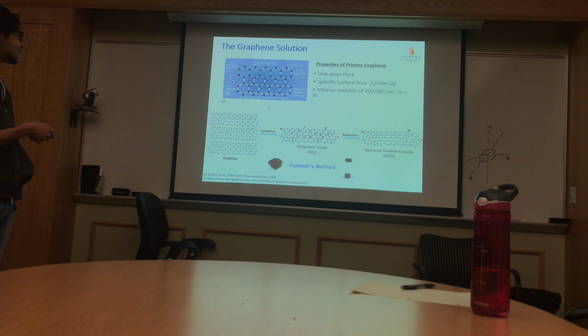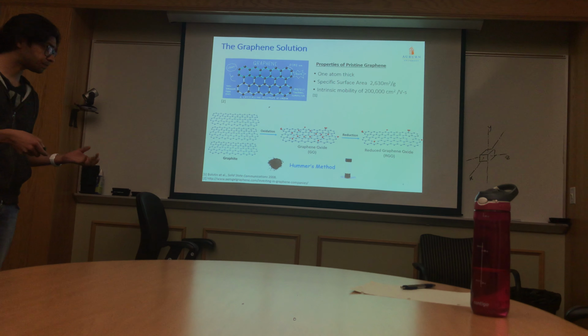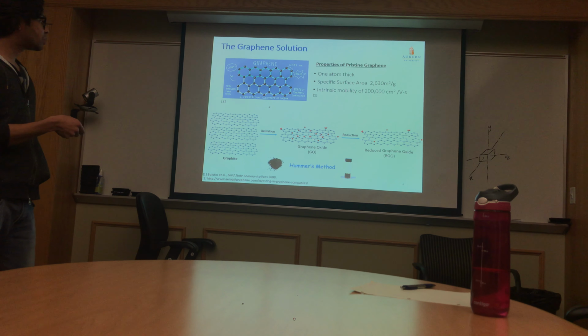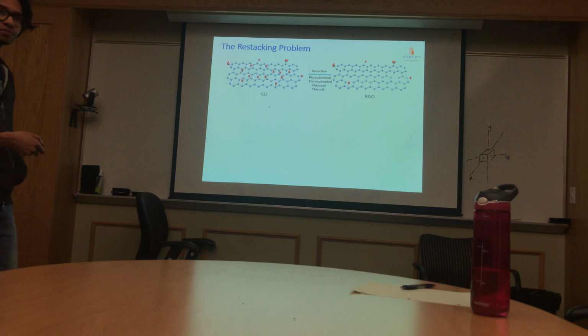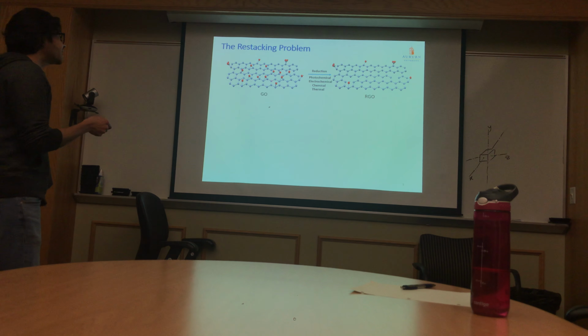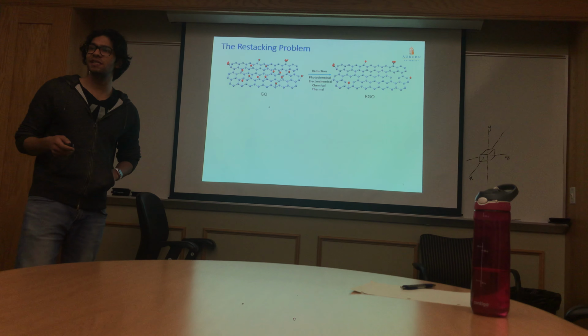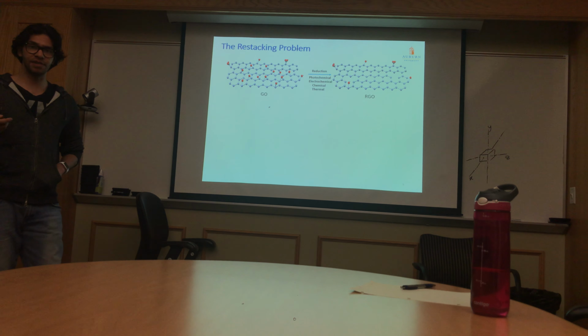Once we oxidize these sheets, they are exfoliated into graphene oxide sheets, which are very well dispersed in water. Now, we need to remove these oxygen functional groups in order to make RGO, and the process is called reduction. It's important to reduce graphene oxide because this material here is an insulator. That means it does not conduct electricity.